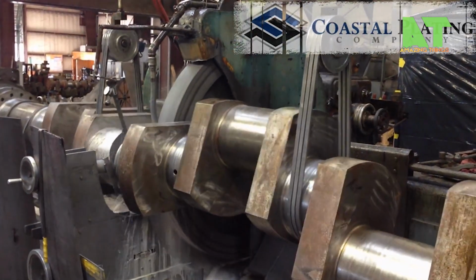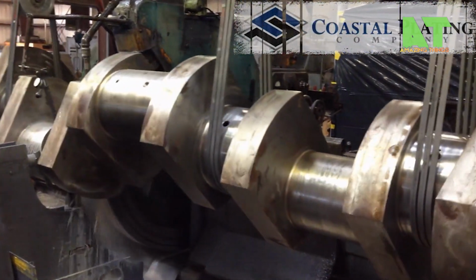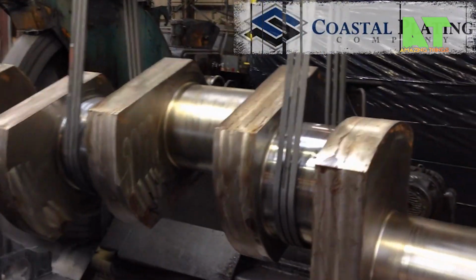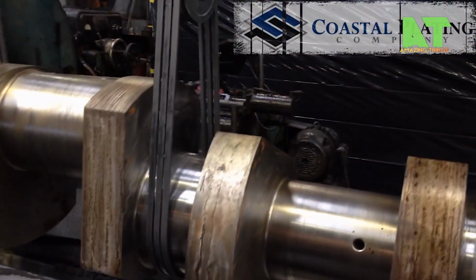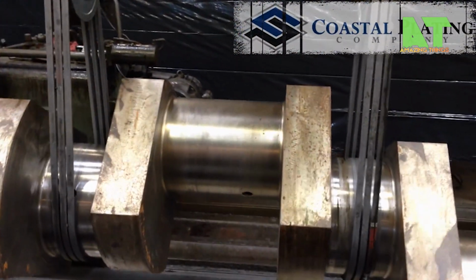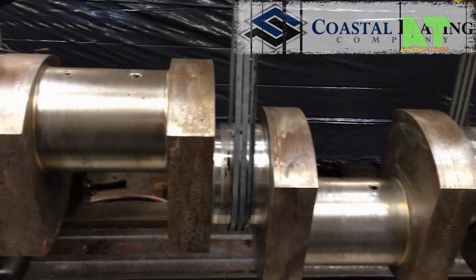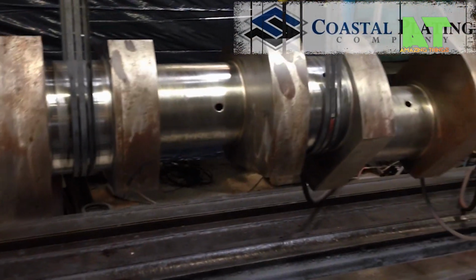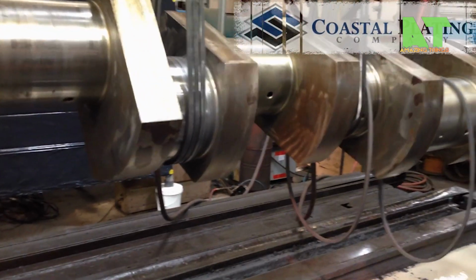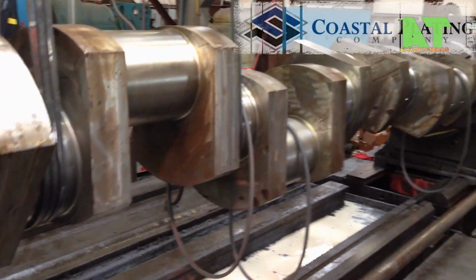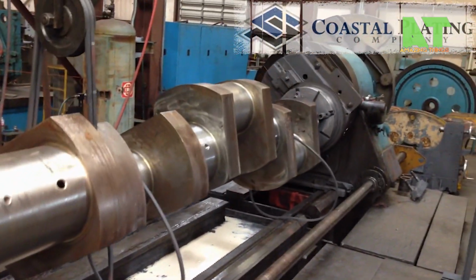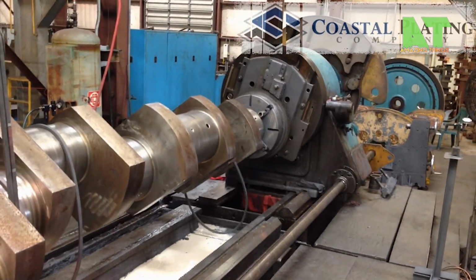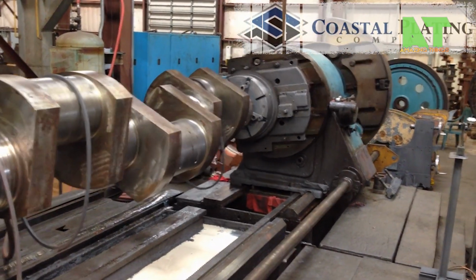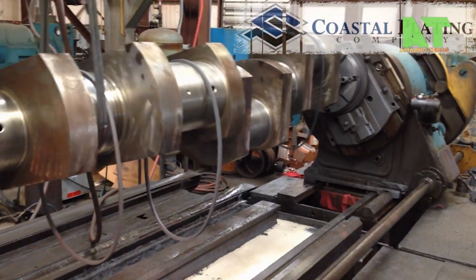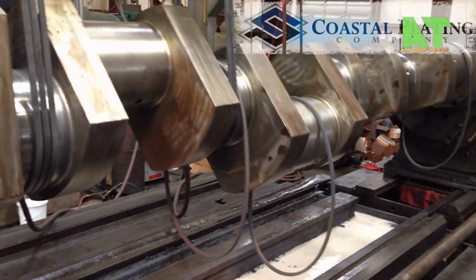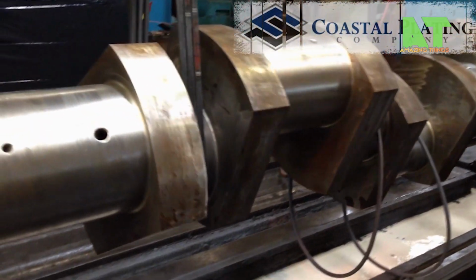Unlike decorative chrome, which is applied in thin, shiny layers for appearance, hard chrome is deposited in much thicker layers, sometimes up to 0.050 inches or more, specifically to restore dimensions and add surface hardness. The process involves submerging the crankshaft in a chrome plating bath, a solution of chromic acid and sulfuric acid, maintained at a precise temperature. Electrical current is passed through the solution, causing chromium ions to deposit onto the steel surface at a controlled rate. It's electrochemistry at industrial scale.